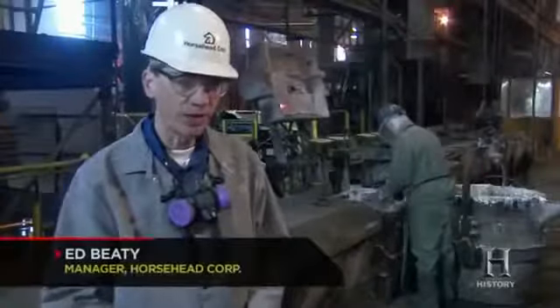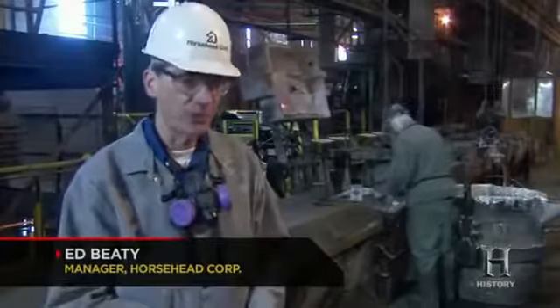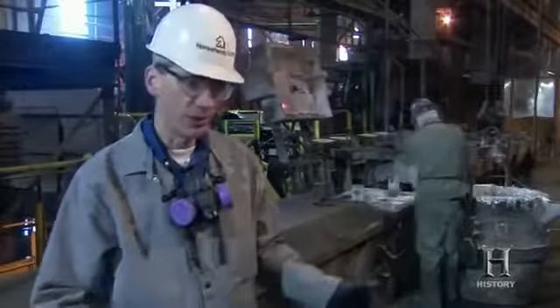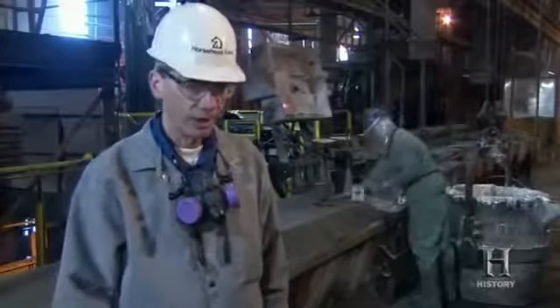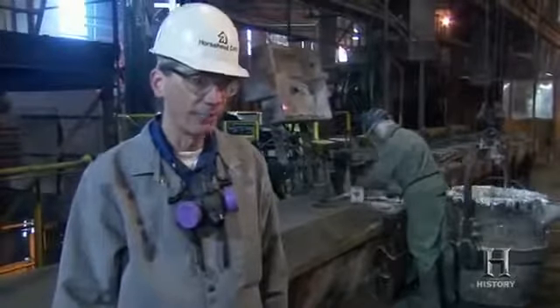The operator now is using skimming boards to remove dross from the surface of the ingots. The dross forms because the zinc has been exposed to air and forms a frothy material that ruins the zinc surface. We want the product to go out with a nice smooth surface, so he skims those off with skimming boards and then closes the top of the ingot mold and allows it to slowly cool and solidify.